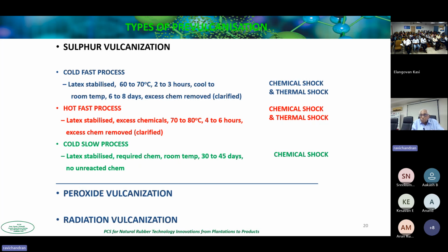And we are clean. We put the chemicals by way of a water-based dispersion into the latex and vulcanize it. The latex remains as a 60% solid, but it's fully vulcanized. So you can now process it in your factory as a vulcanized latex product. And you don't have to wait to do everything and then have it vulcanized at the very end. And we have basically 3 processes: the cold fast process, where latex is heated to 60 to 70 for 2 to 3 hours and cooled, and 6 to 8 days of maturation.